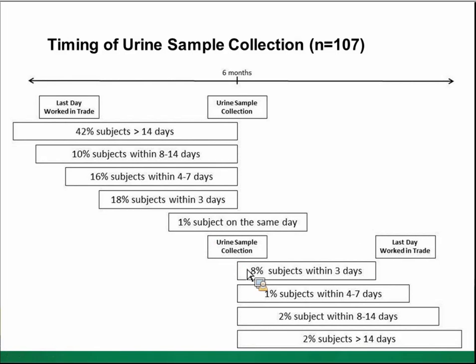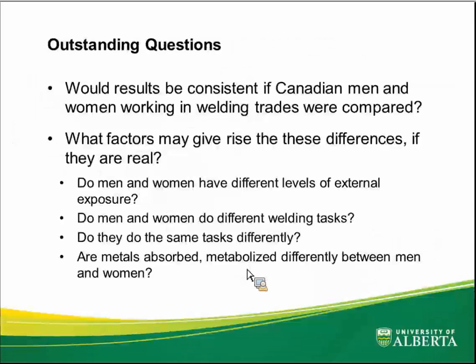And so this is a little bit more information on that. This is not from the 45. This is from a much larger sample of the urine samples. This was just to give you a feel for how much it did vary. If we were hoping to have the urine sample collected on the same day as the questionnaire, only 1% did that, and then about 20% within the preceding 3 days, and it goes back. And if you look in the other direction, because people received the reminder to collect the urine sample and the reminder to complete the questionnaire at the same time, some people collected the urine sample before the day at work, before they completed the questionnaire. So the order was not consistent.